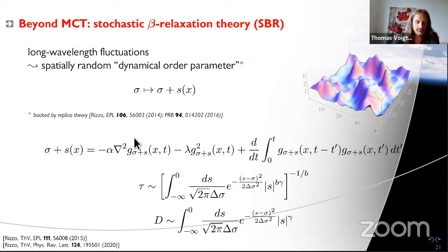So again, we have an audience to whom I can show this, I guess. What we have in the center of the slide here is a version of the beta scaling equation, as originally derived in the context of mode coupling theory by Goetze, with a few added terms. So let's walk through them. In the original theory, you had a distance parameter sigma to the glass transition, and there was a scaling function called g of t, the beta scaling function, that obeyed the following equation. It had a parameter lambda, which is called the exponent parameter, times the square of the function, balanced by the convolution of the function with itself. And on the other hand, we just have the distance to the glass transition.